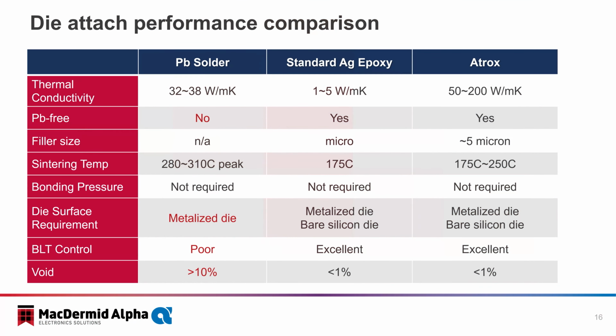Let's look at the performance comparison to other technologies. We're comparing traditional leaded solder, the standard silver epoxy or ECA, and the Atrox product line. You can see the thermal conductivity is dramatically different. Atrox does not contain any lead, and there's no bonding pressure required. It simply relies on a heat profile to create a sintering mechanism.